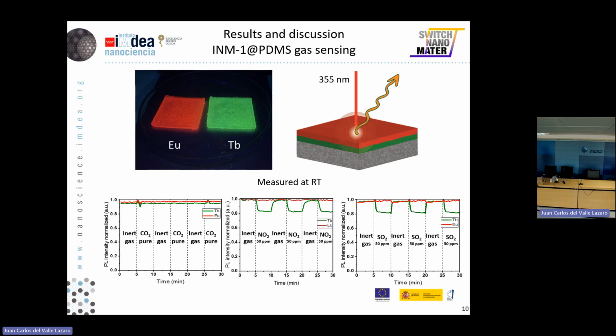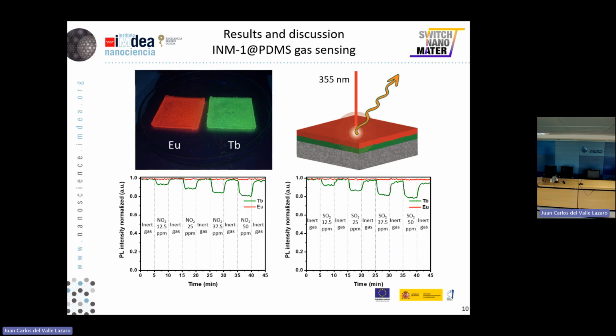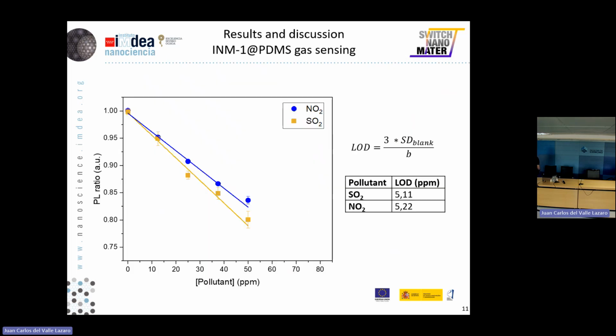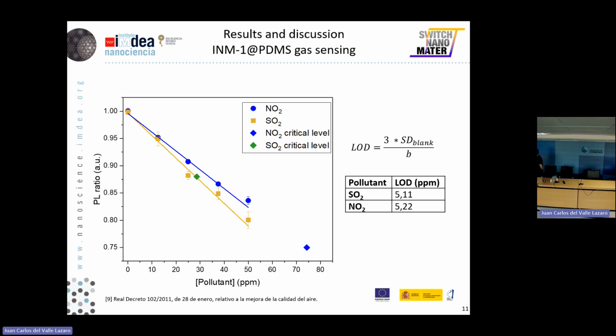This led to the possibility of obtaining a ratiometric sensor where we can use these materials for different concentrations, in which we can see that the luminescence of the terbium decreases gradually as the concentration is higher for NO2 and SO2, allowing us to develop this calibration, where we obtain a limit of detection for both materials of about 5 ppm. Results that are lower than the limit set by the Spanish government.